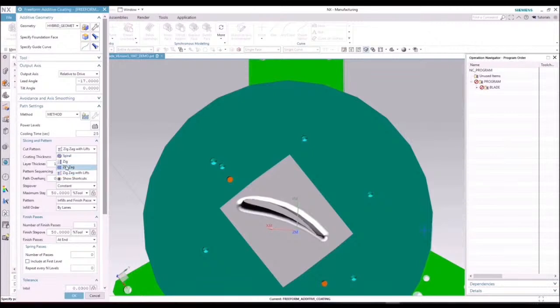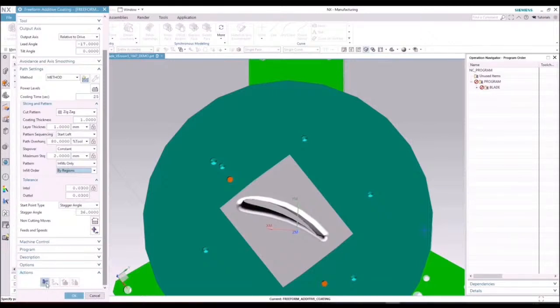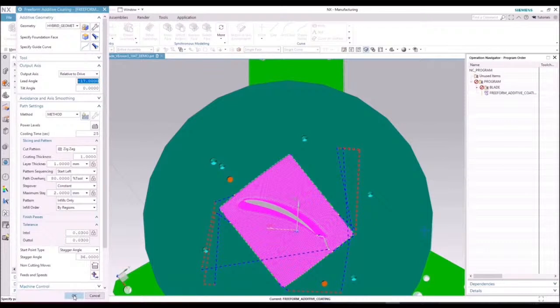The tool path strategy needs to be defined in accordance with the given component shape and the surface topology. In our example, the surface region to be coated is homeomorphic to a cylinder surface. The spray tool is to be moved primarily in the circumferential direction around the airfoil. Secondarily, it is to move in vertical direction following either a helical line or a vertical stack of tracks, each alternating in direction. Further parameters having to be set comprise basic coating properties such as the single path thickness and total layer thickness, the path start and end points, path overhangs, and geodesic path separation distances.